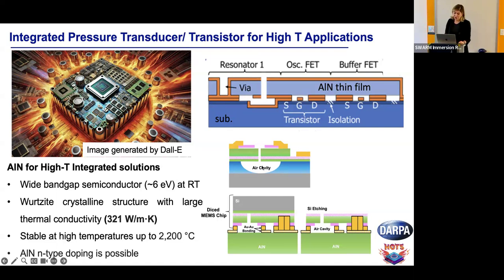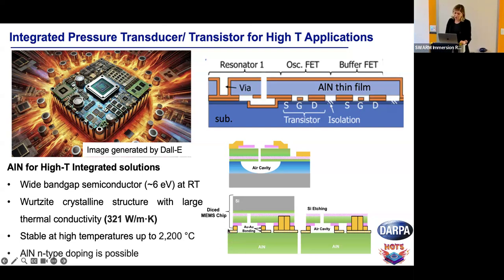Some of the things that I showed earlier all had a sacrificial layer or even the silicon layer, which was etched with xenon difluoride to create these suspended membranes. But here I want to show you how we can actually use flip chip bonding to bond the MEMS die to the aluminum nitride substrate, or to any substrate, basically. We are choosing aluminum nitride because we care a lot about coefficient of thermal expansion, CTE. Due to the very high temperatures, it's important to have both of these layers be of the same kind. Otherwise, the thermally induced stress will just peel off the MEMS part.